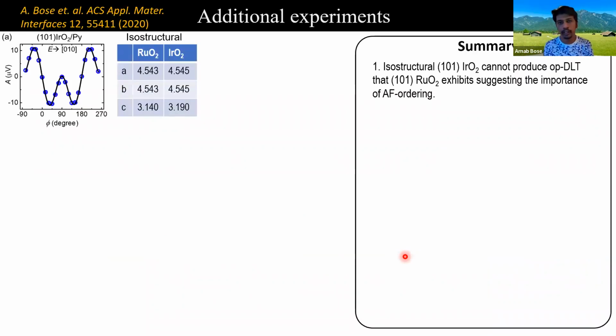So we also did some other control experiments. For example, we did similar studies on 101 oriented iridium dioxide thin films and permalloy bilayers. We run current in the same direction, but we don't see any extraordinary spin orbit torques in iridium dioxide. We studied iridium dioxide because iridium dioxide is isostructural as compared to ruthenium dioxide. Both are rutile oxides, and their lattice constants are nearly the same.